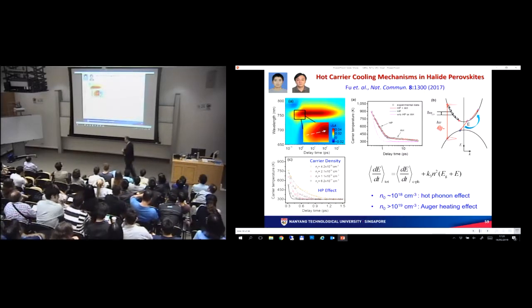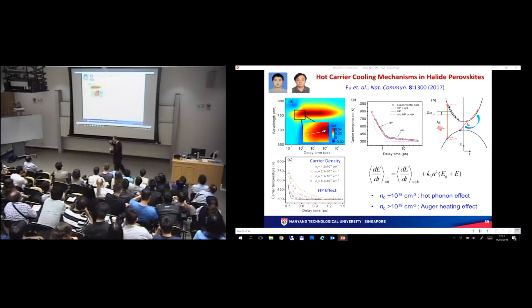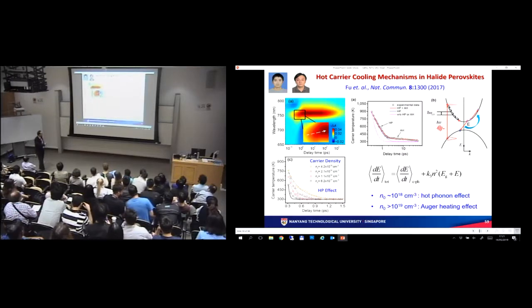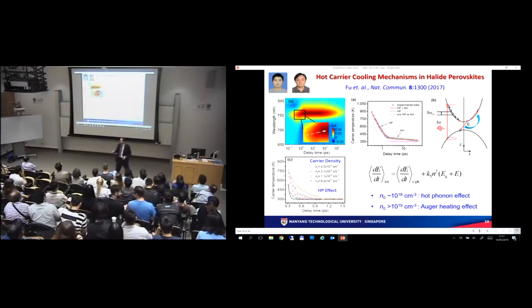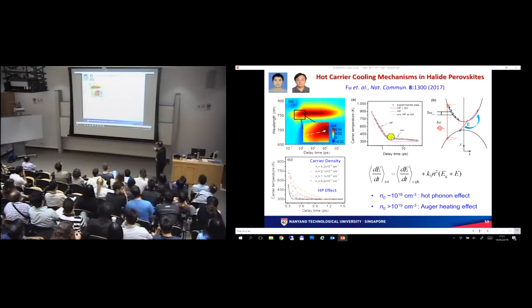Now they came out with a model that tracks the rate of population increase of phonons from LO phonon emission and LO phonon absorption, and then we tested the model as a function of hot carrier temperature, as a function of temperature, as a function of pump fluence. From our experimental data, the model is able to explain all this data fairly well. What we have here is a plot of the energy loss, taking care of the electron-phonon coupling and the Auger heating process, and that gives you a fairly good fit over these various delay times.